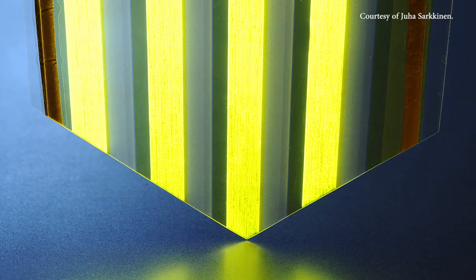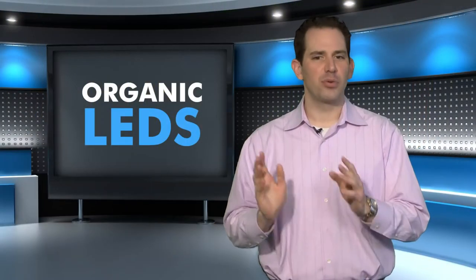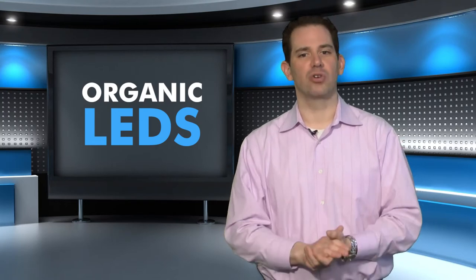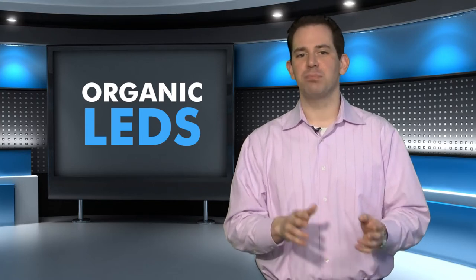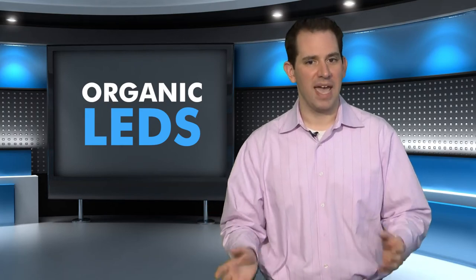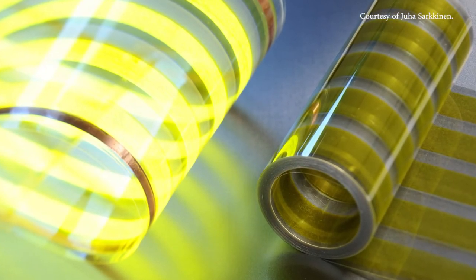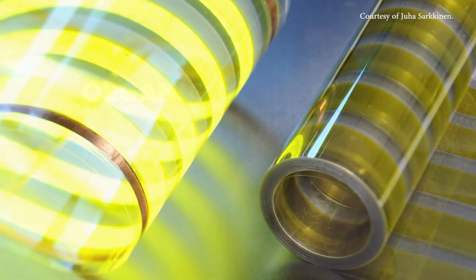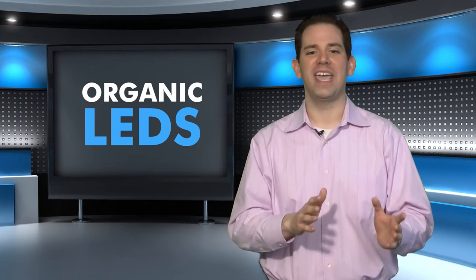That light surface has electrodes and multiple polymer layers embedded within it, and each of those are only a few hundred nanometers thick. Traditional LEDs have three times the luminosity of their organic counterparts. But OLEDs can do something LEDs just can't do — they emit light across the entire surface area, whereas LED is a spotlight technology. VTT's plastic OLED film will only work for about one year as of now, because the polymer materials are degraded over time by oxygen and moisture. Its lifetime will be extended as screen protector technology and the applications themselves continue to grow. One application being looked into right now is the use of OLED light as a medium for data transmission. And if you're already aware of the term the Internet of Things, you know that we're going to see a lot more from these printed, flexible, organic diode-laced surfaces.